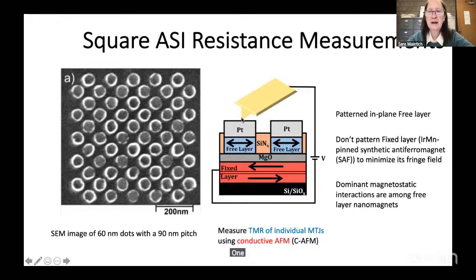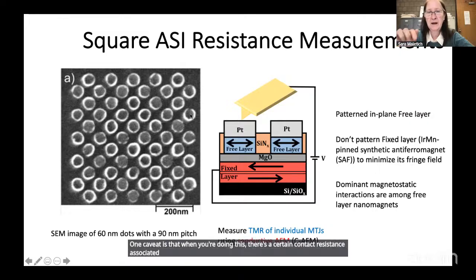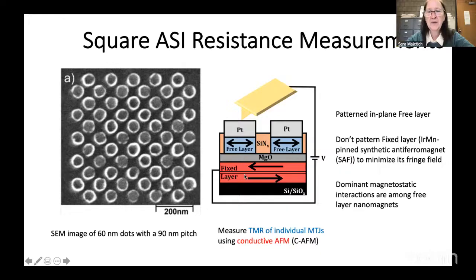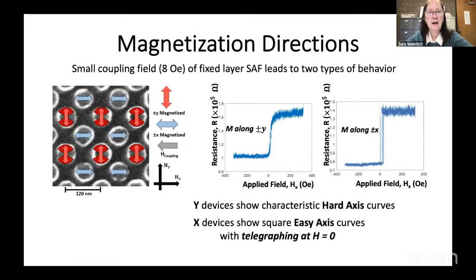One caveat is that when you're doing this, there's a certain contact resistance associated with making electrical contact with one device, then the next, then the next. And that's about 200 ohms. And with the resistance of a tunnel junction, 200 ohms is small, and so we can neglect that. But if you had an all metallic device, the contact resistance could be a problem. So what do we see? When we look at the individual devices, we look at the resistance and we scan the field in the X direction, and we see these blue curves here, scan up, scan back.